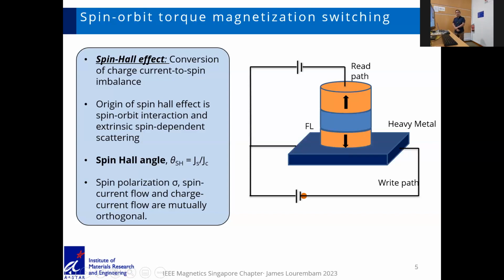So a brief background. The spin orbit torque MRAM, or the memory technology, the basic element is a magnetic tunnel junction. Unlike a traditional two-terminal magnetic tunnel junction, this one has three terminals, where the read and write paths are separated. One would send the electrical current in the write path, which is typically a heavy metal, and by the property of the spin orbit interaction in the heavy metal, there is spin imbalance in the heavy metal, which would lead to a torque on the ferromagnet sitting just above it. And this is how one could switch the magnetization of the ferromagnet. The read is basically tunneling magnetoresistance in this case.